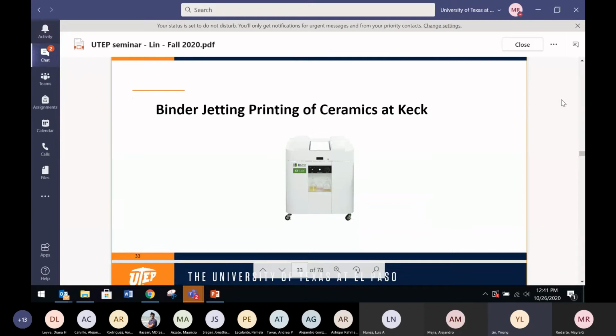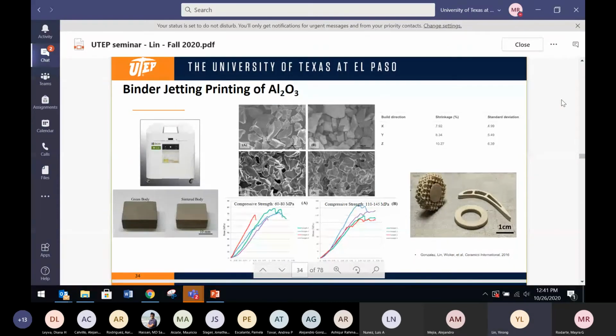All right, so I'll give you some overview slides of what we do with ceramics, right? First of all, the binder jetting. Next slide. So what we did here is we started with alumina. As we know, alumina is pretty much the most commonly used ceramic, right? So all the ceramic tubes you guys use for sintering or the high temperature isolation materials, a lot of them are based on alumina, right? So we printed it, we did the sintering, and we can print different geometries. As you see over here, after sintering, we can increase the compressive strength by about double, right? So that's good. Next slide.